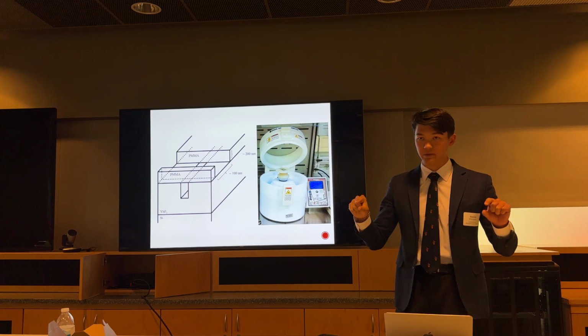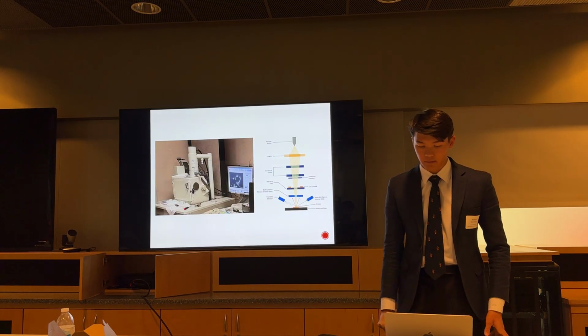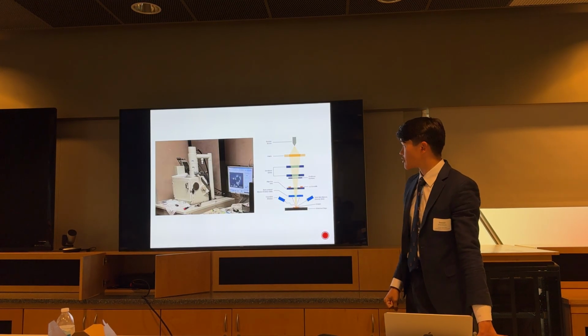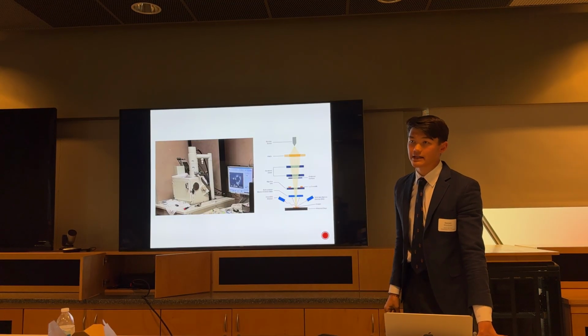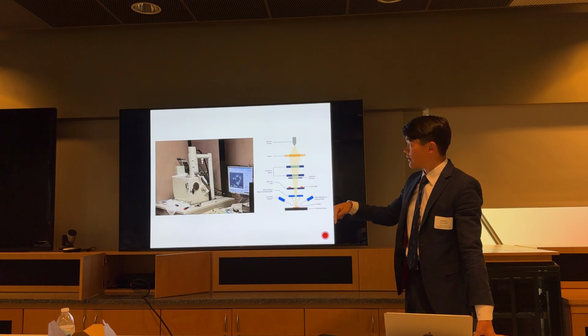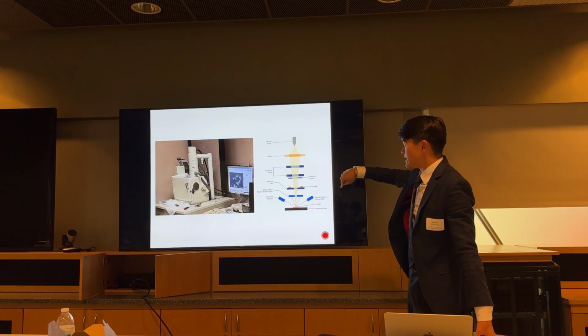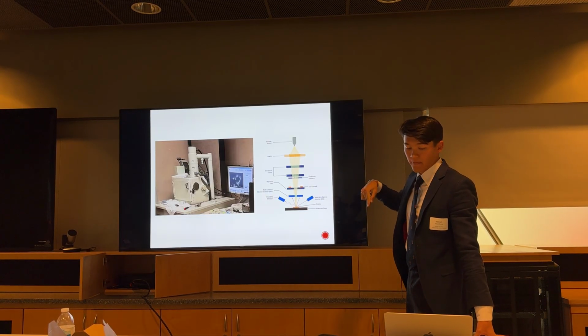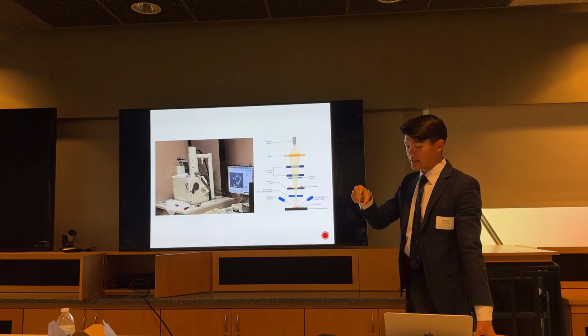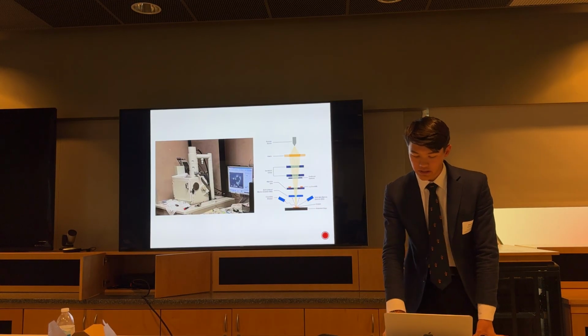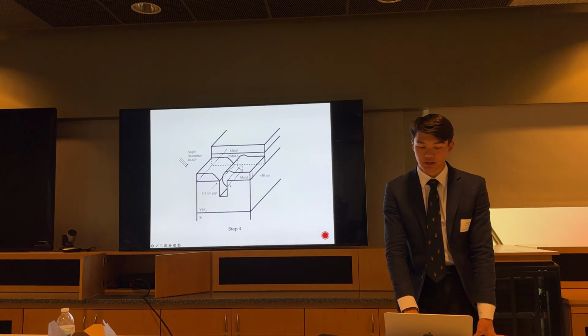Once we have that layer of PMMA, we then use a device like this, a scanning electron microscope, so slightly less complex than a scanning transmission electron microscope. And this electron beam can also be scanned along the top of the sample, and we create exactly the trench that we need, which is sideways to the main ytterbium fluoride trench.